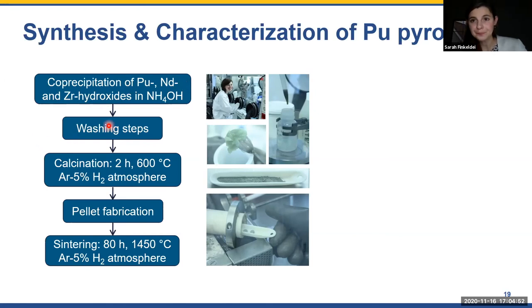And when you precipitate neodymium and zirconium hydroxides first, you might get one precipitate, and then you precipitate the plutonium, and then the advantage of a very homogeneous precursor might be gone. So I had to tune a lot with the parameters, with the acidification and the pH values and concentrations of the entire system, to suppress plutonium polymerization.